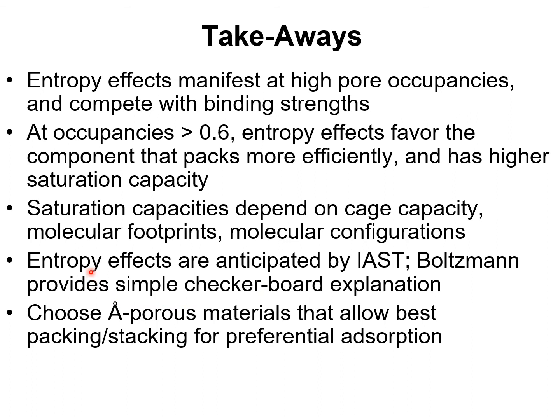In general, entropy effects are correctly anticipated by the ideal adsorbed solution theory, but the Boltzmann equation for entropy provides a simple explanation of entropy effects on the basis of a metaphor using a checkerboard that represents the different binding sites.